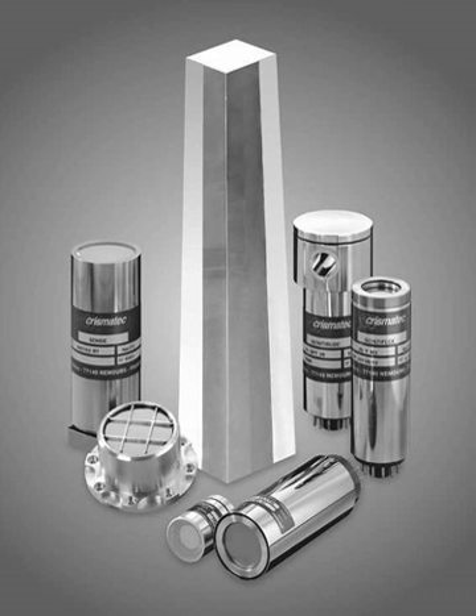Newly developed products include LaCl3(Ce), lanthanum chloride doped with cerium, as well as a cerium-doped lanthanum bromide, LaBr3(Ce). They are both very hygroscopic, i.e., damaged when exposed to moisture in the air, but offer excellent light output and energy resolution, 63 photons per keV gamma for LaBr3(Ce) versus 38 photons per keV gamma for NaI(Tl), a fast response, 16 nanoseconds for LaBr3(Ce) versus 230 nanoseconds for NaI(Tl), excellent linearity and a very stable light output over a wide range of temperatures. In addition, LaBr3 offers a higher stopping power for gamma rays, density of 5.08 g per cc versus 3.67 g per cc for NaI(Tl).